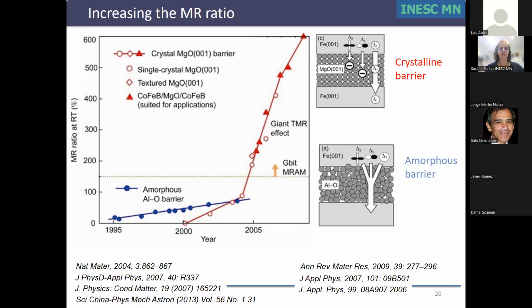And I did work myself on aluminum oxide tunnel junctions, and then suddenly people found out that there are other options that could potentially lead to much higher magnetoresistive ratios. These were textured and crystalline materials that would have coherent tunneling between the states of the two magnetic electrodes. Compared with an amorphous barrier, which is the case for aluminum oxide, the MgO barriers looked much more promising. In fact, in 3 to 4 years, people could demonstrate from 0 to 600% magnetoresistance at room temperature.